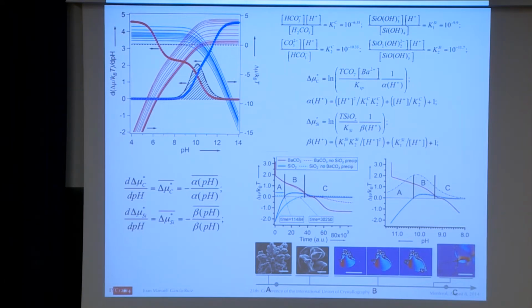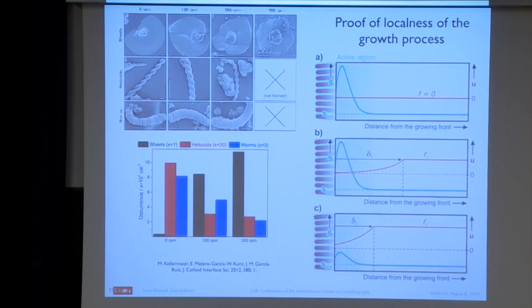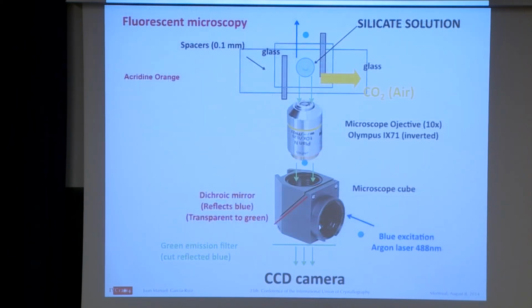So what we show here is that when you solve the chemistry of the coupling of the two precipitations, the silica and carbonate, okay, you really have a maximum, I mean, the possibility to have this kind of structure only in the pH window in which we actually observe this phenomenon, okay? So the problem is that we submitted this paper, and the referee said, okay, this is very good, but you have to show it. And then the point is how to measure the pH, right? How to measure the pH here.